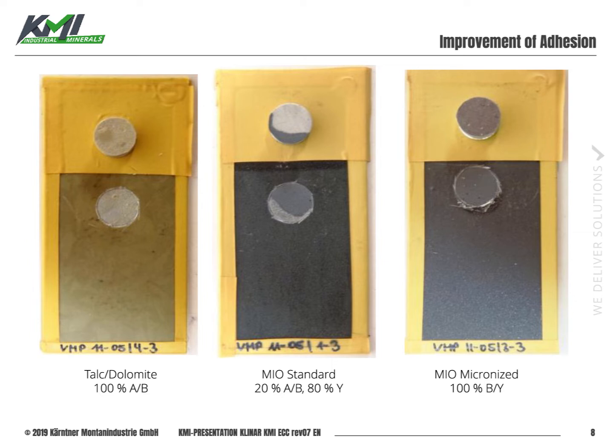pigment volume concentration. We did the pull-off test, and what you can see here, with the talc dolomite mixture you have 100% failure between substrate and coating. With the MIO standard you already have 80% adhesion and only 20% failure, already a big improvement. And with the new micronized grade you have 100% adhesion between substrate and coating, which is really a remarkable improvement. So if you have issues with adhesion on difficult to coat surfaces or problems with the intercoat adhesion, Miox is really in a position to improve these adhesion problems.